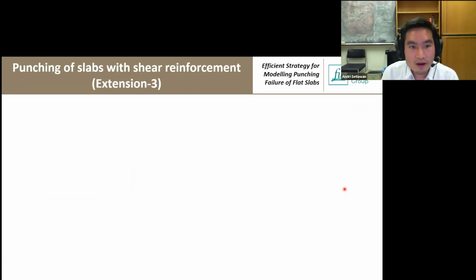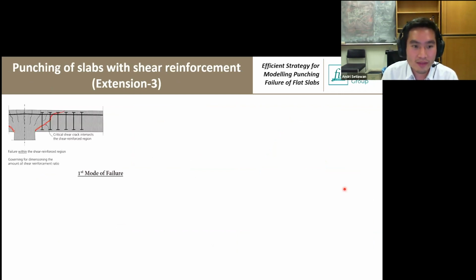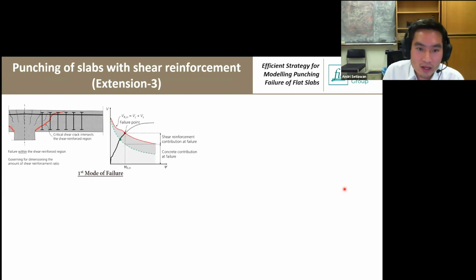So lastly, for the slab with shear reinforcement, we consider two different scenarios. The first mode of failure is when you have the critical shear crack intersecting the shear reinforced region, and the behavior is more controlled by the yielding or the straining of the shear reinforcement. So we have this criterion already from the critical shear crack theory, so we can just add the contribution of shear reinforcement as a function of the rotation. So this is pretty much simple, to be honest, because the model is already available.